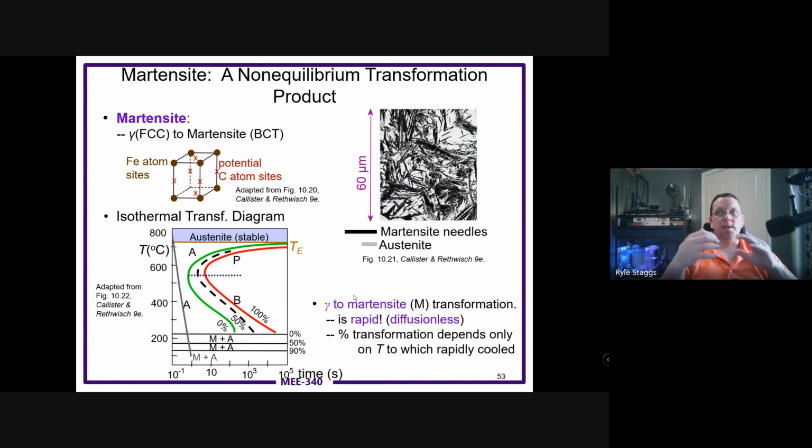So you can see on the right side, these are like sharp shards all going different directions. If you imagine trying to apply a force and squash those materials, it has support going in all three dimensions, and it's just not going to want to move or shift. All of those jagged edges have extremely high energies associated with them trying to move or slide past each other, simply based on the principles of friction alone. So there aren't a lot of directions where there are slip planes for these to move past each other